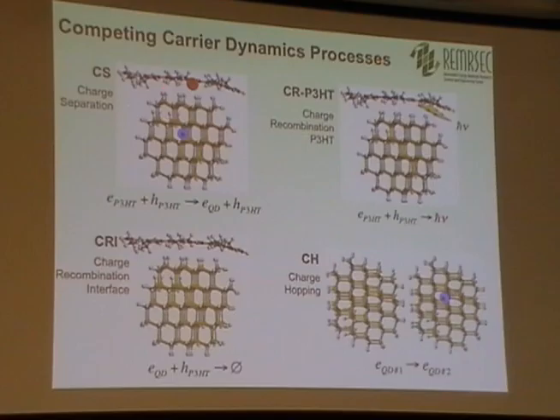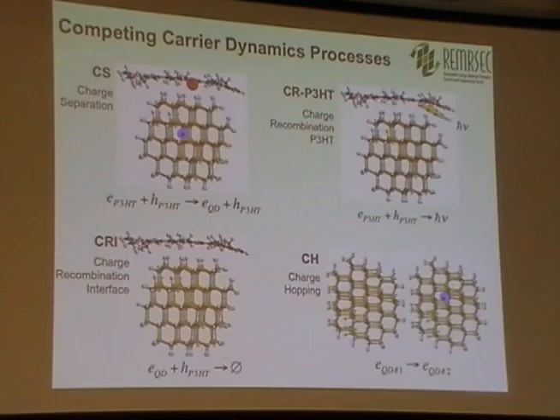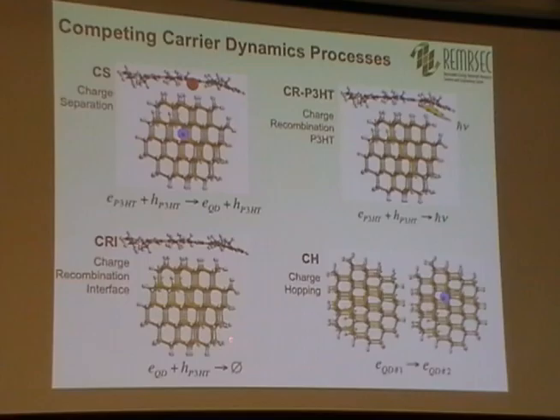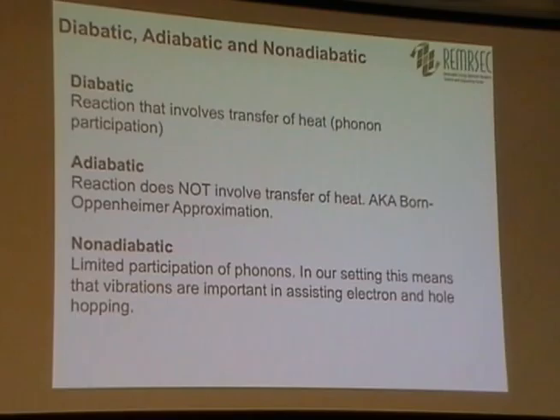Here's what we're interested in. We have an electron-hole pair generated on the P3HT, and the electron drops down to the silicon quantum dot — we want to look at the rate of charge separation. Another possibility is that the exciton just recombines, and we look at the rate of charge recombination CR on the P3HT. We also want to look at the rate at which the charge-separated, dissociated exciton recombines into an exciton sitting on the P3HT — charge recombination from the interface. Finally, we look at electron hopping between two adjacent silicon quantum dots. I want to calculate the rates of all of these processes.